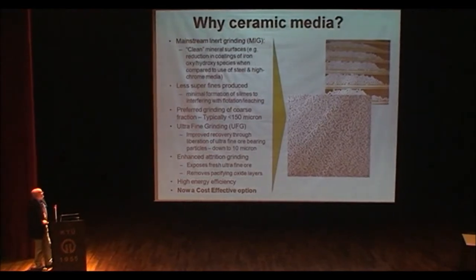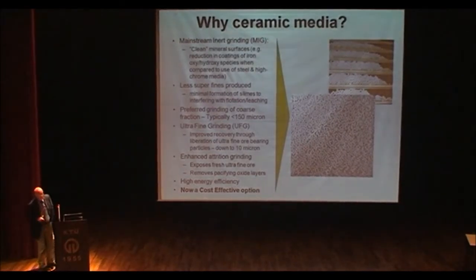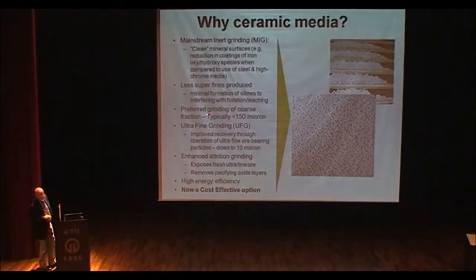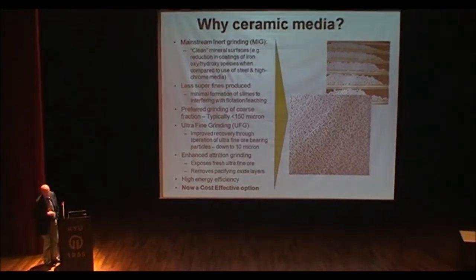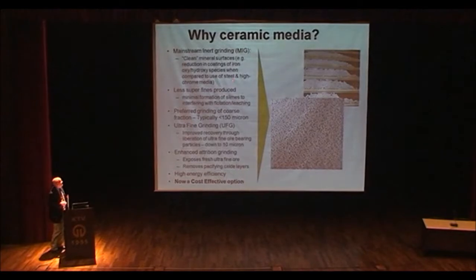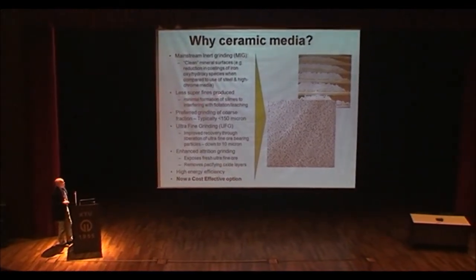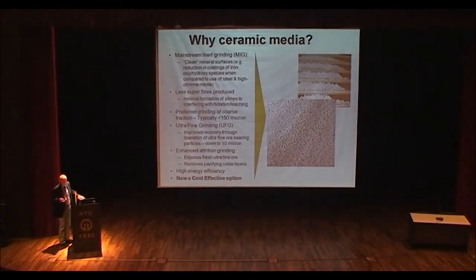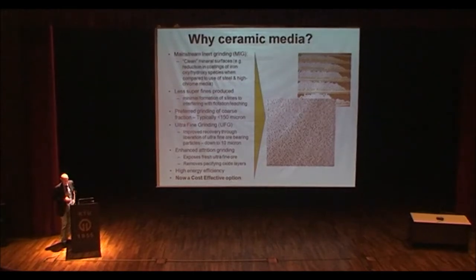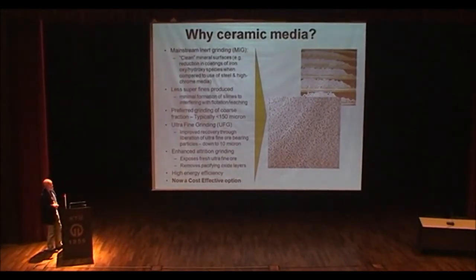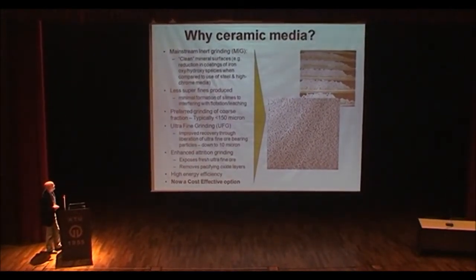Why ceramic media? Well, apart from the fact that the main thing is if you're milling extremely fine, and I'm talking about going down to 10 microns and ultra-fine grinding, you have far less fines than you would do in a conventional steel milling with large balls, which create a lot of slimes. And again, in hydrometallurgy, slimes are one thing you don't want.